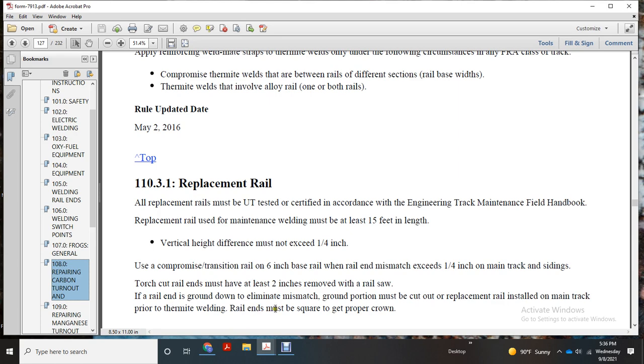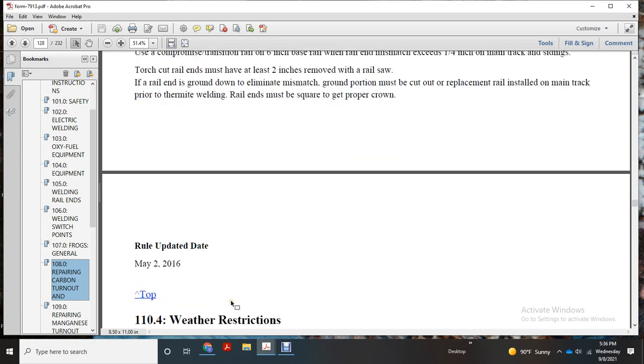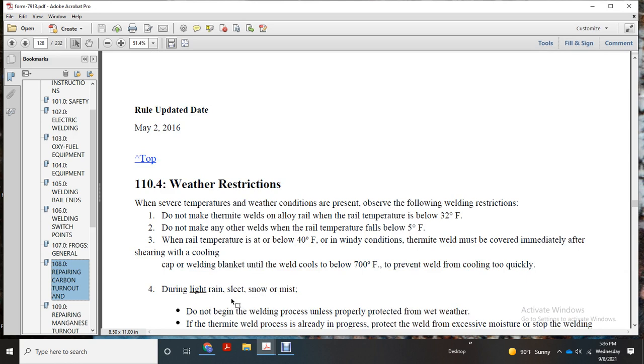Prior to thermite welding, rail ends must be squared and have the proper crown. Weather restrictions: observe the air temperature, and if cold weather conditions are present, observe the following precautions. Do not make thermite welds on alloy rail when the rail temperature is below 32 degrees. Do not make any other welds where the rail temperature falls below 5 degrees.